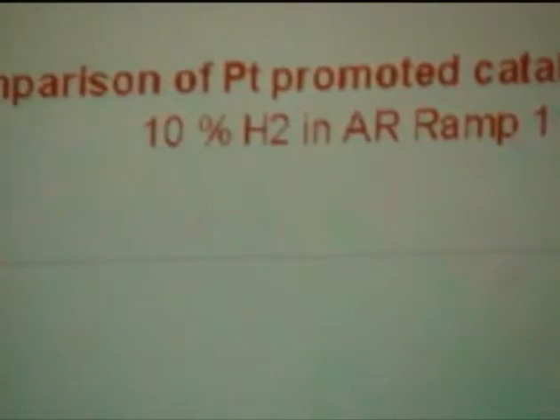These are more recent data from our laboratory, from George Huber et al. We're comparing the temperature programmed reduction spectra for a platinum promoted cobalt on silicate catalyst compared with the unpromoted catalyst, blue for unpromoted, red for promoted. There's a significant shift in the peaks for reduction to lower temperatures with the addition of the platinum promoter.